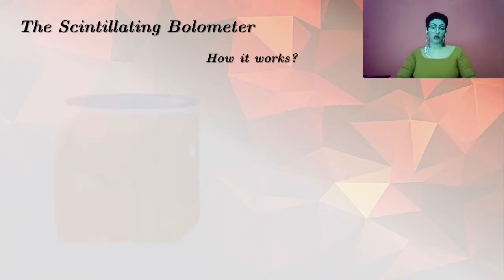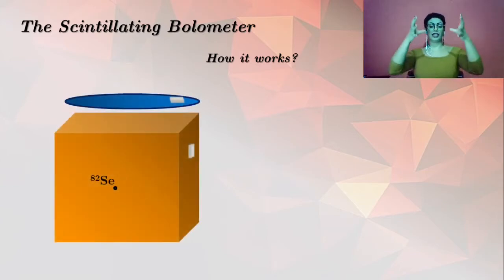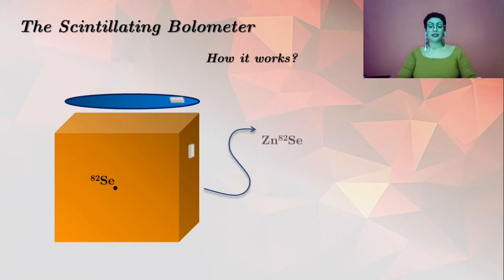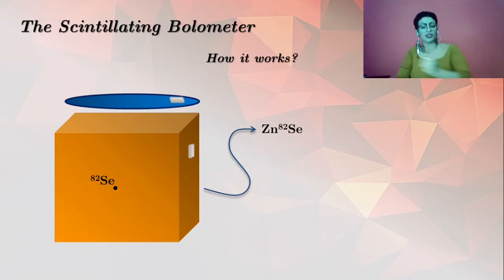So how does it work? The core of a scintillating bolometer is made of a material with good thermal conductivity and good scintillating luminescence properties, where the particle interaction will occur. In our case, this material is a zinc selenide crystal enriched with the selenium isotope. Coupled to this material, we have thermistors for measuring the thermal variation of the material, and a light detector for measuring the light signal.